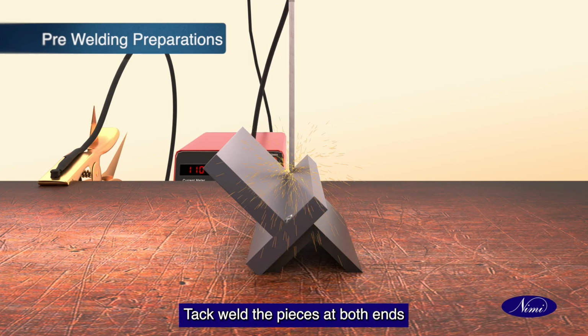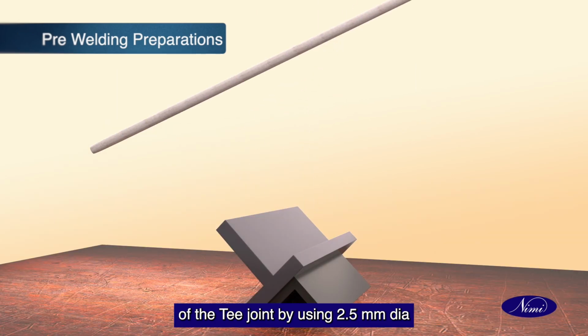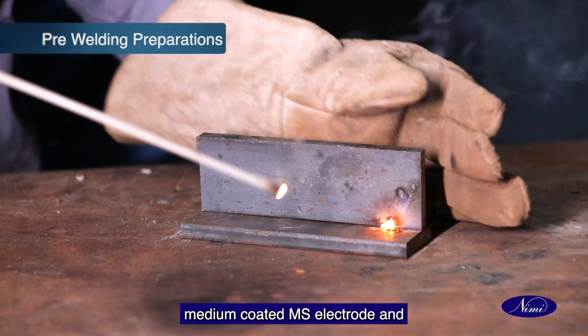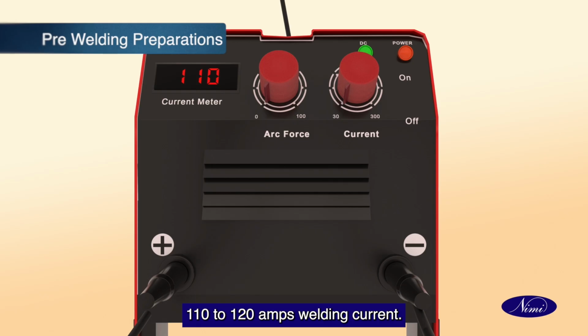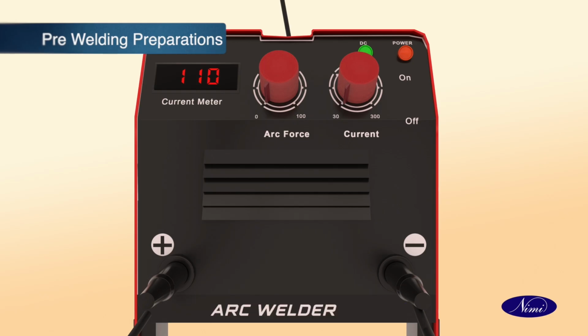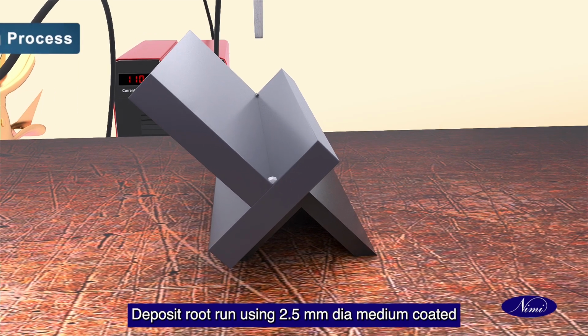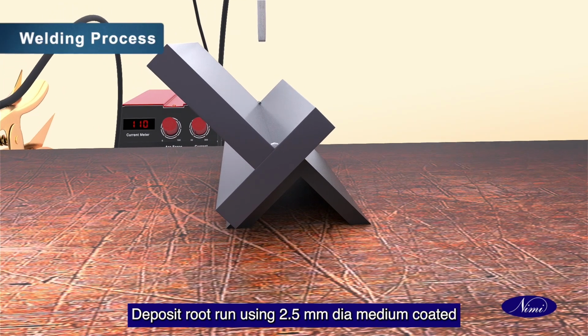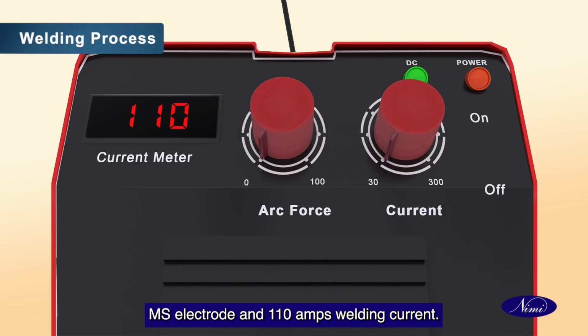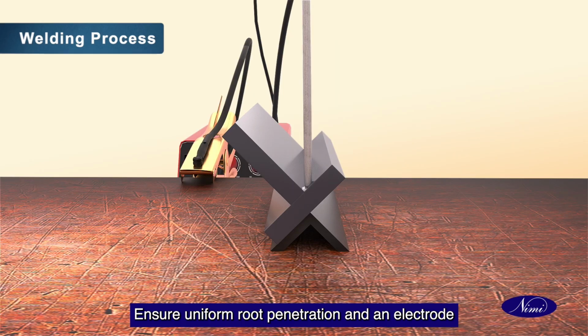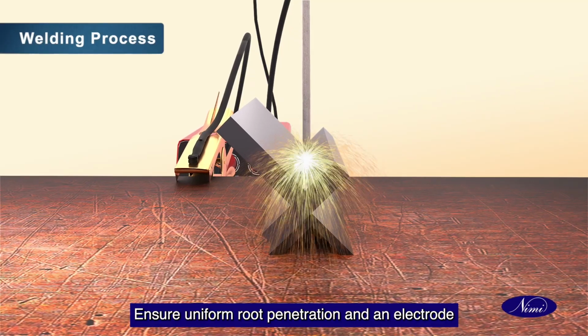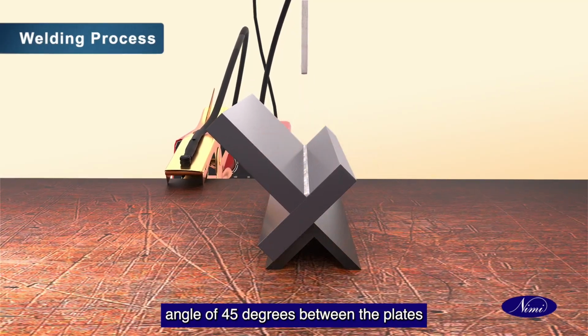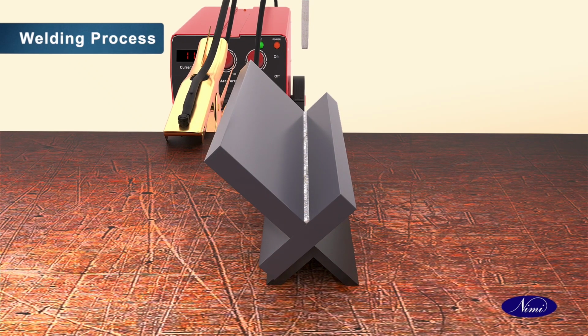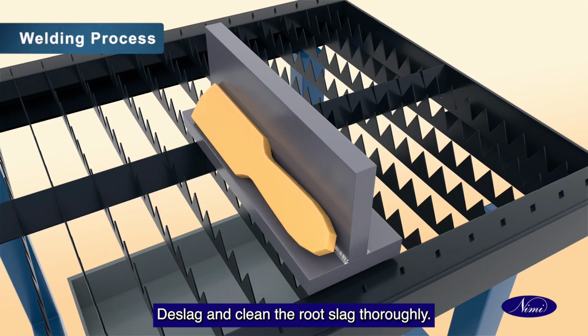Tack weld the pieces at both ends of the T-joint by using a 2.5 mm dia medium coated MS electrode and 110 to 120 amps welding current. Deposit root run using 2.5 mm dia medium coated MS electrode and 110 amps welding current. Ensure uniform root penetration and an electrode angle of 45 degrees between the plates and 80 degrees with the weld line. Deslag and clean the root slag thoroughly.